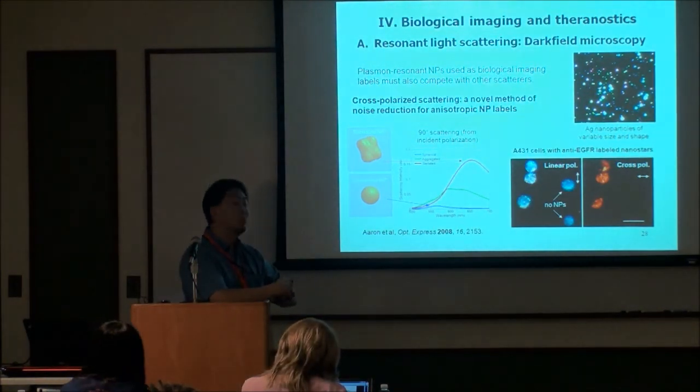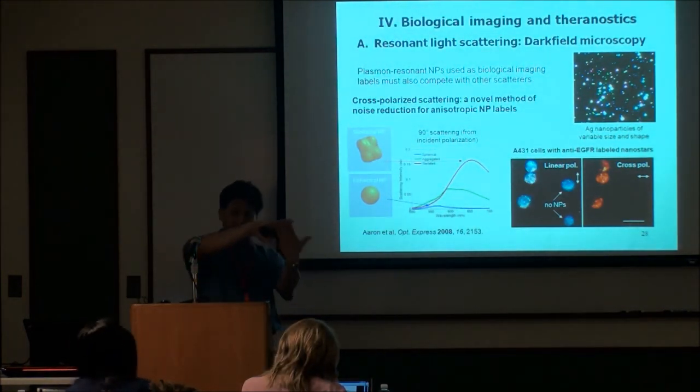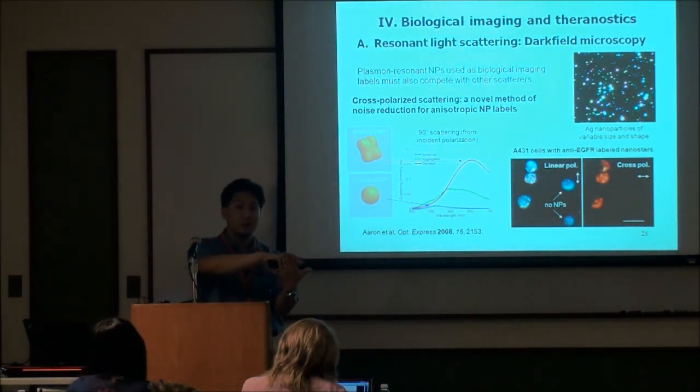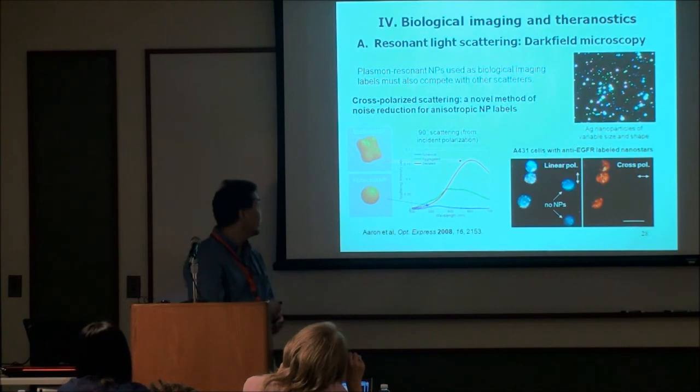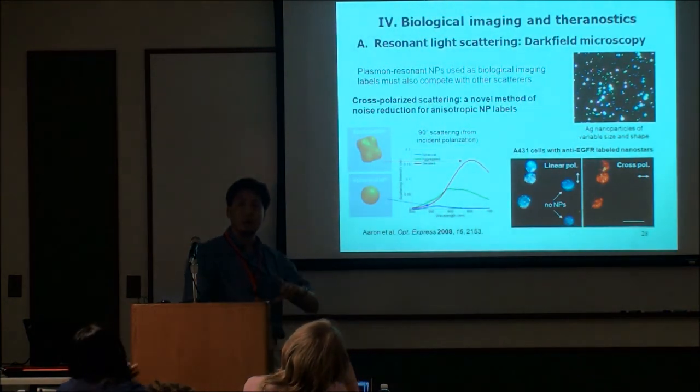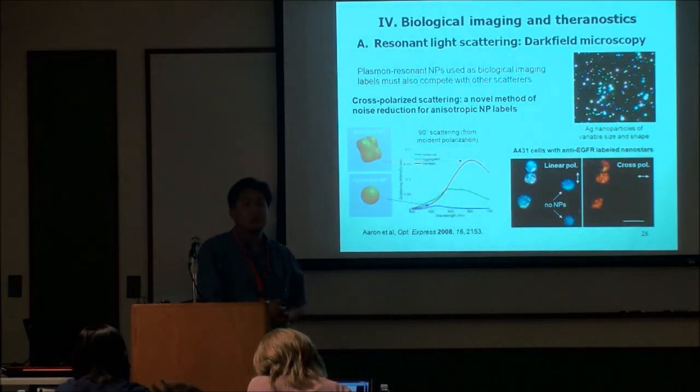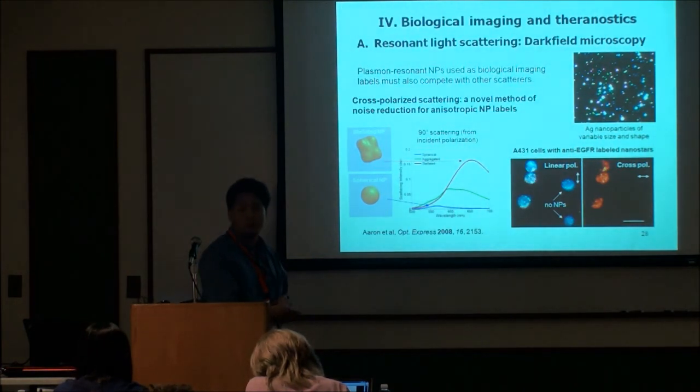depolarization. So, you know, if you take two polarizer plates and put them at 90 degrees, right, in principle you should not get light coming out after crossing both planes. But if you put particles like this in between, this can cause a significant depolarization of the light and allow for some leakage. Okay, this gives rise to some very nice opportunities for being able to increase the quality of your signal, right, in the presence of a strong background.